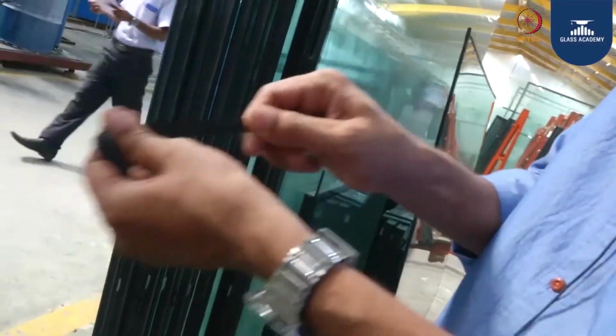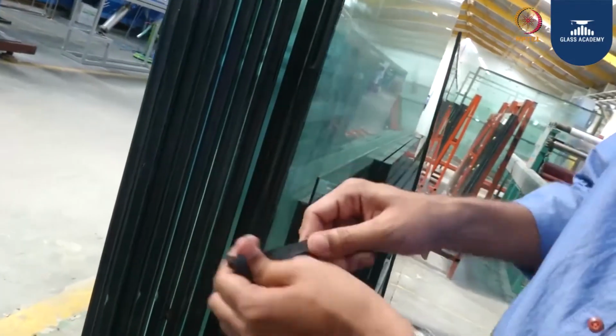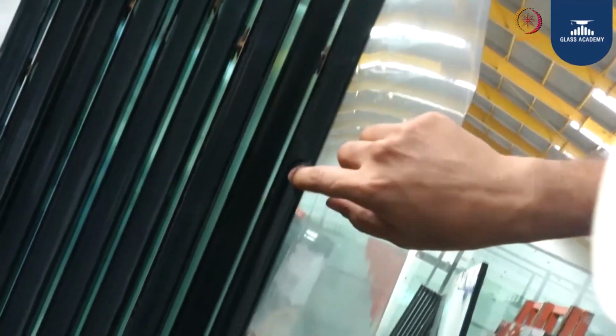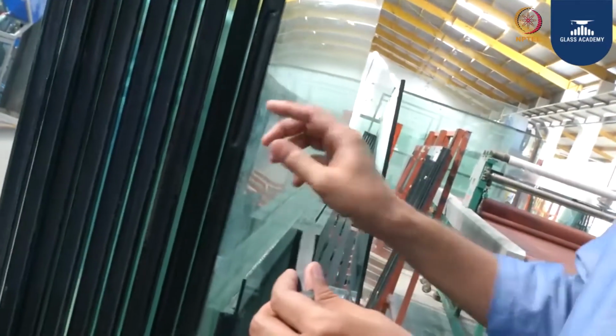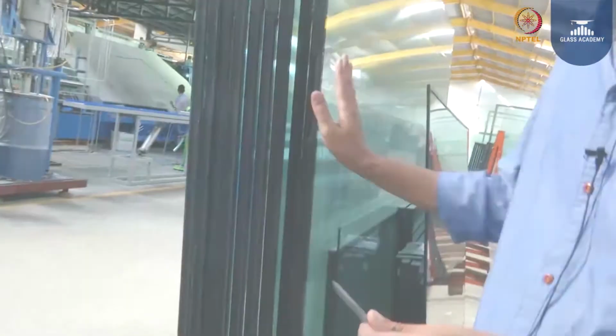The silicone should always have an elongation property, and when we cut it, it doesn't come off directly. Some part of the silicone still adheres to the glass and the spacer, showing that the bonding between the glass, spacer and silicone is good. This is known as the silicone peel adhesion test.